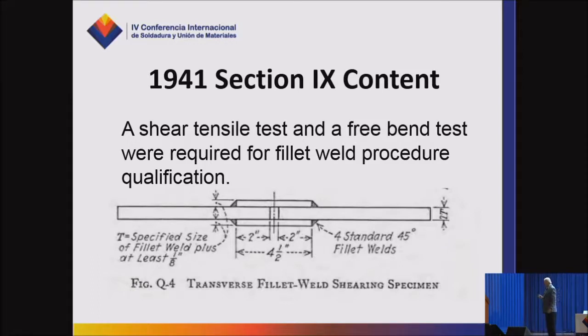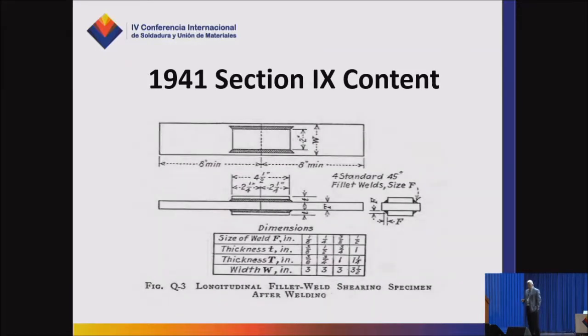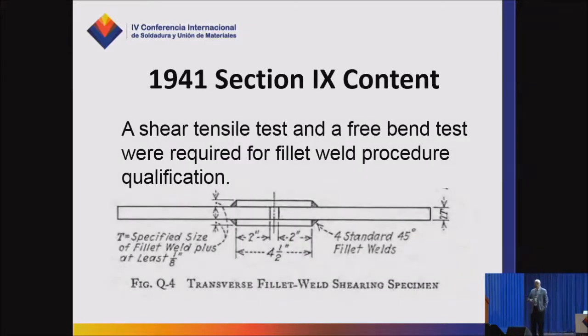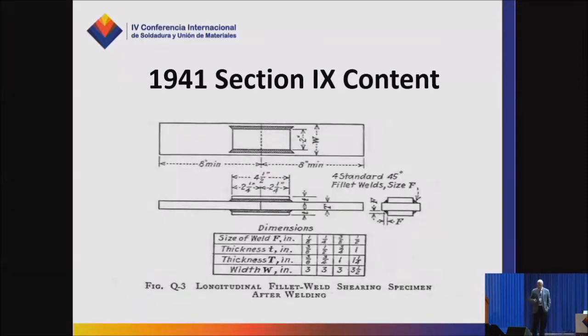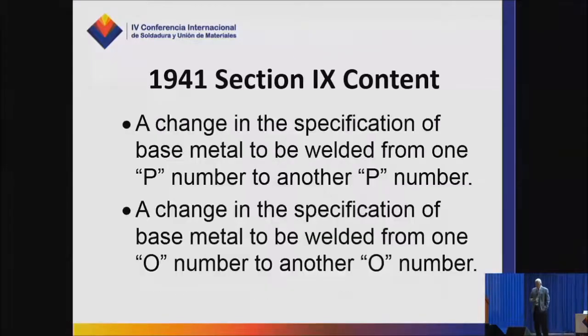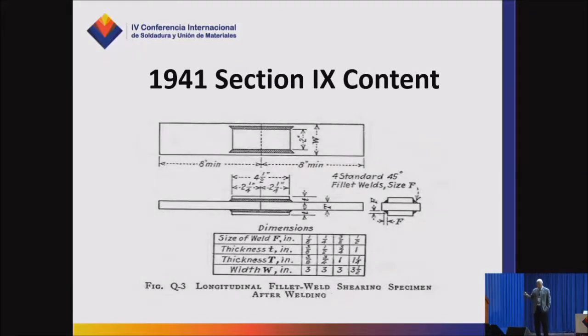You also had to do a tension test if you were going to make fillet welds. You had to do a tension test, a shear tension test, and a free bend test for fillet welds. So a shear tension test looked like this. And then there is a second shear tension test where instead of the welds, in this case the welds are transverse to the joint. In this case the welds are parallel to the joint. You had to do a tension test, and it had to pass certain criteria.